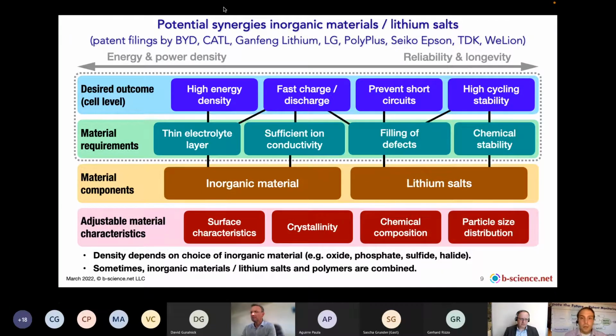I have also included additional diagrams. I would certainly be happy to share the presentation. So this is the combination of inorganic materials with lithium salts, especially if the eutectic lithium salts melt at a fairly low temperature. One can basically do a melt infiltration of an inorganic thin film that often contains some pores or some cracks. So this is an interesting approach, combining lithium salts with inorganic electrolytes.